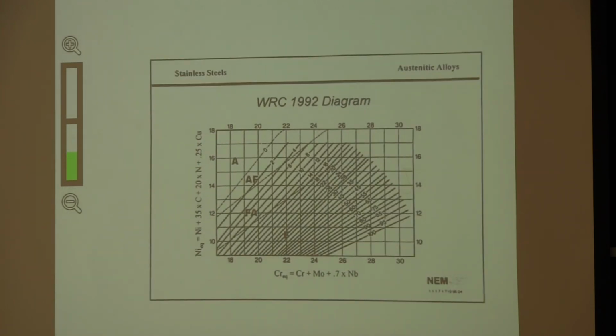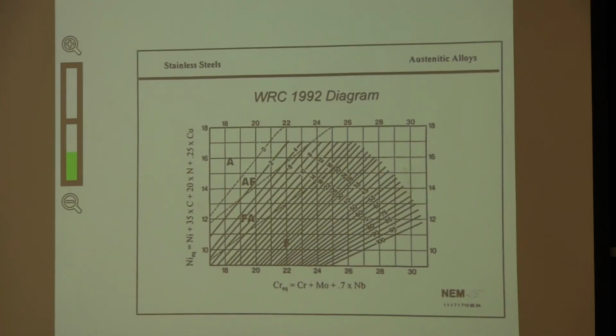Something that was developed much later than the diagram that I showed you earlier, the Schaeffler diagram. This was developed by the Welding Research Council, so it's called the WRC 1992 diagram. And what they did is they modified these chromium and nickel equivalents, and basically this is the region between austenite and ferrite, so it's just a small section of that Schaeffler diagram. They also drew on here the solidification modes. So above this line here you get completely austenitic solidification, and you can then see the AF and the FA and the F-type solidification as well on this diagram.